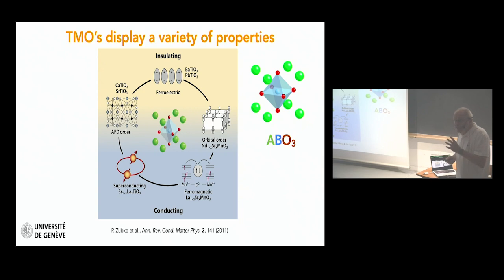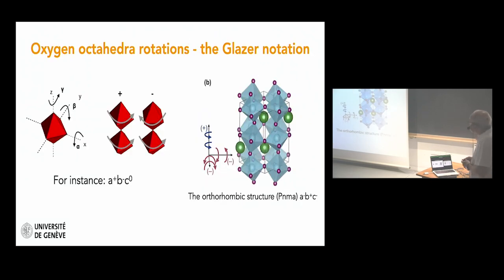Now, it's important to know how to describe these rotations, and there is a rather nice way to describe them. This is what is called the Glazer notation, quite easy to understand. The Glazer notation uses three letters, a, b, c, and these letters describe the rotations around the three pseudocubic axes: a along the x-axis, b along the y-axis, and c along the z-axis. The letter is linked to the amplitude of the rotations. If you have two times the same letter, it means the same amplitude of rotation. If you see a plus, it means that the rotations are in phase. If you have a minus, it's out of phase, and 0, no rotation.